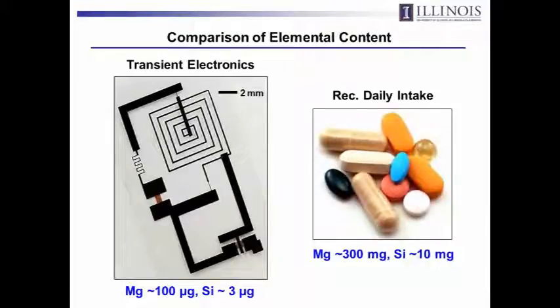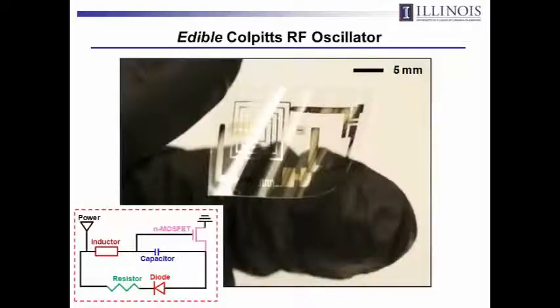So one additional point I'll just make is that the materials appear to be biocompatible and implantable. They're also safe to eat, and in fact they're good for you, because it has magnesium, it's got silk, it's got silicon. If you look at a daily vitamin, one single vitamin tablet has about 300 milligrams of magnesium and 10 milligrams of silicon. That's 3,000 times more of those elements than are found in that circuit. It's because these films are so thin that the total mass content is minimal. And by the way, the same elements are found in a daily vitamin anyway. So it turns out you can actually eat these things.